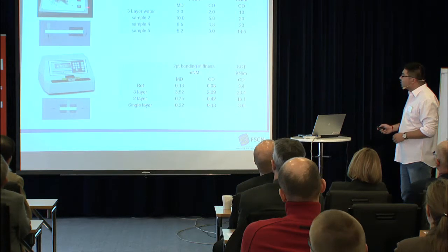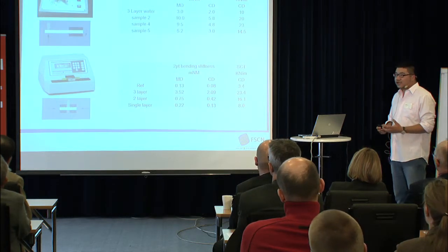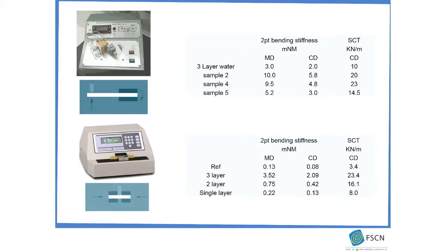And we use two simple methods to determine the result of our materials. One is the 2-point bending stiffness. It has a clamp to hold the paper samples, and it starts to turn at a certain angle. From the ISO, we use the 15 degrees measurement. And here is the force sensor to check how much bending resistance. And then after the calculation, we can turn that into the bending stiffness. The second one is the short compression test. It collapses the paper sample and pushes it towards each other at a very short gap to check how much force it needs to collapse the materials.